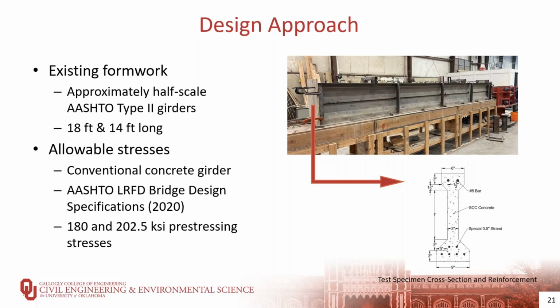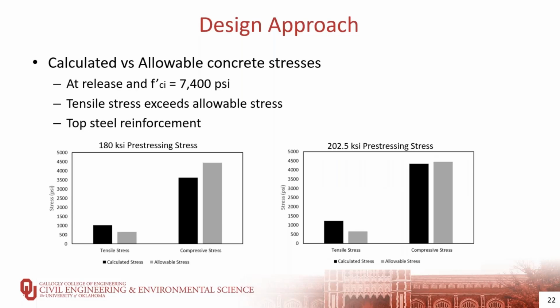Allowable concrete stresses at end regions and midspan were calculated following AASHTO LRFD bridge design specifications for both pre-stressing stresses of 180 KSI and 202.5 KSI. The tensile, compressive, and allowable stresses of the pre-stressed girders at end regions are presented in these figures using the conventional concrete compressive strength of 7,400 PSI at release.